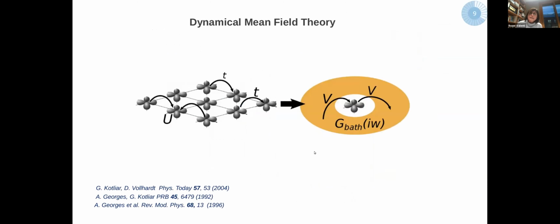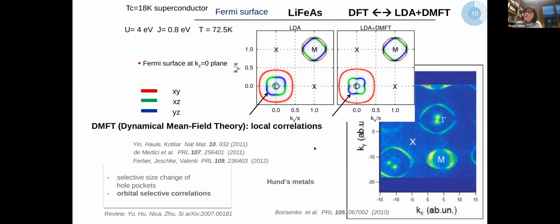Now, a theory that has been very successful in describing these effects of correlations in iron-based superconductors is dynamical mean field theory, which yesterday there was a session on, where this was in fact discussed. The idea of dynamical mean field theory is to replace the system of interacting orbitals by a system of one central site, which is dynamically interacting with a bath given by the rest of the sites. And in fact, this combination of dynamical mean field theory with density functional theory has been able to describe many trends observed in the correlations in these materials.